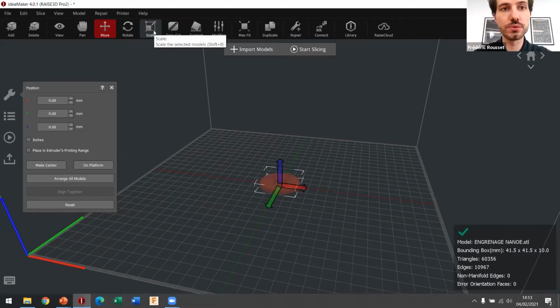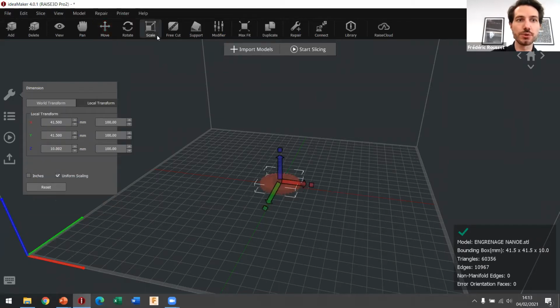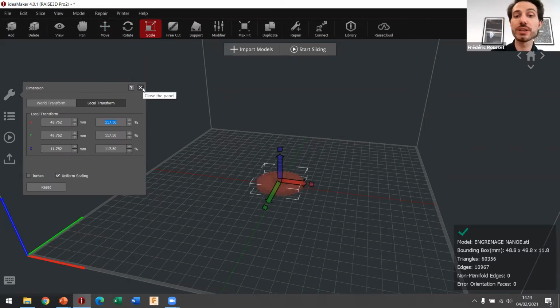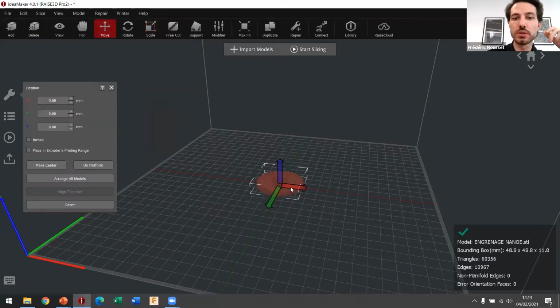So first of all, the first thing that you have to do is on the slicer. The slicer is Idea Maker. This is the slicer that is used for Raise 3D, but it is an open source slicer, so you can use it with any other printer. First, you have to do the scaling of your piece. I know the scaling, of course, for the H13, but those are some values that we are providing. This is the value you need because you will have a shrinkage after the sintering. You have to scale up your piece a bit if you want to have the right dimensions after it. Of course, you can also move your object on the bed.